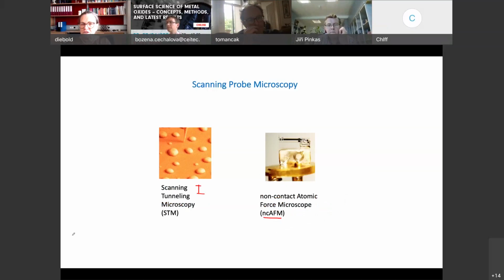And here, what we measure, you can see this from here to here to here. That looks like a tuning fork, right? A tuning fork has its own resonance frequency. So we use it, for example 440 hertz, to swing it, and it resonates with one single resonance frequency. And here is also a little tip mounted, and we measure the change in the resonance frequency for non-contact AFM. So in one case, we measure the current with scanning tunneling microscopy, or we measure the change in frequency when we bring this tip and the sample close together.